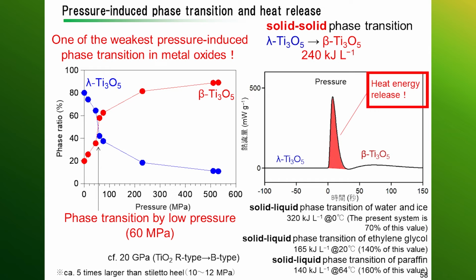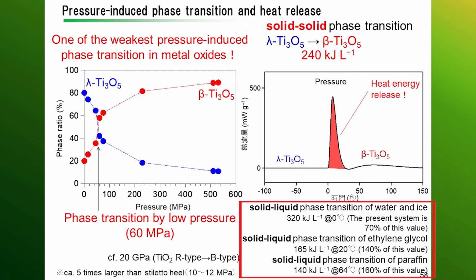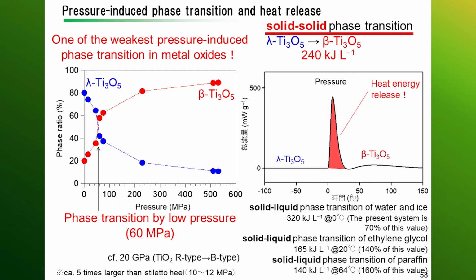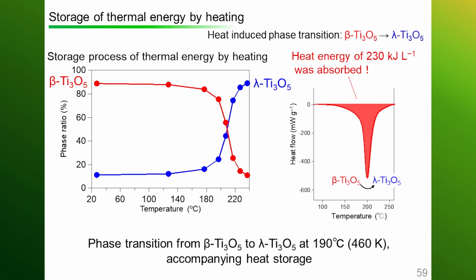And when it changes under pressure, the material radiates heat. From lambda we apply pressure, and at beta it releases heat. That's the phenomenon we observed. The heat energy was 240 kilojoules per liter. As you can see below, the solid-liquid phase transition of water and ice is 320, and for ethylene glycol 165, for paraffin 140 kilojoules per liter. These are typical solid-liquid phase transitions, but this is a solid-solid phase transition, and it can release comparable heat energy.